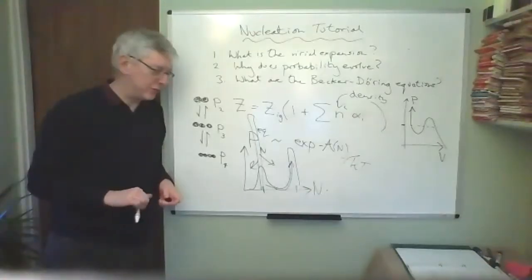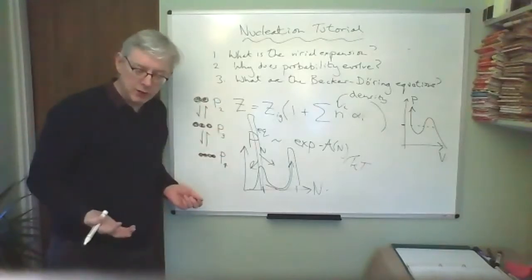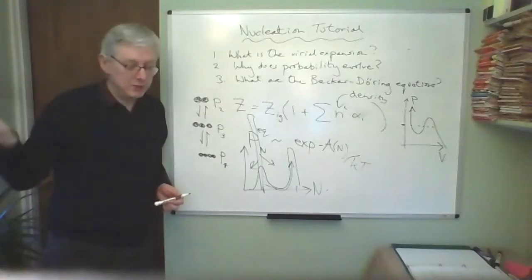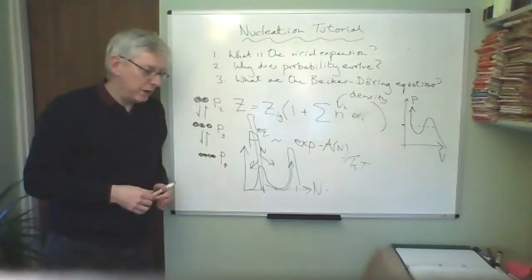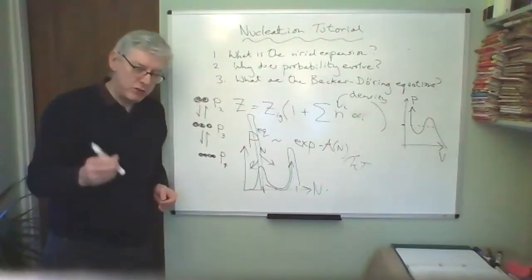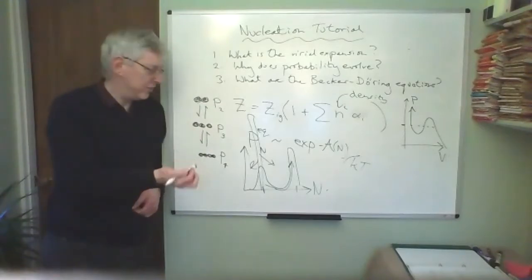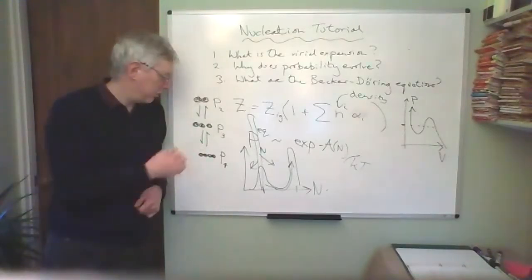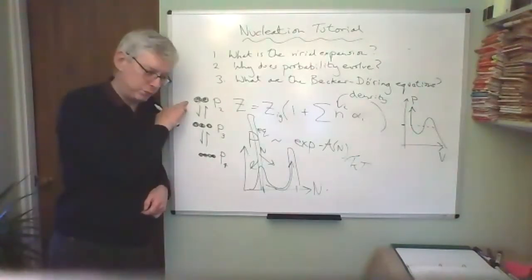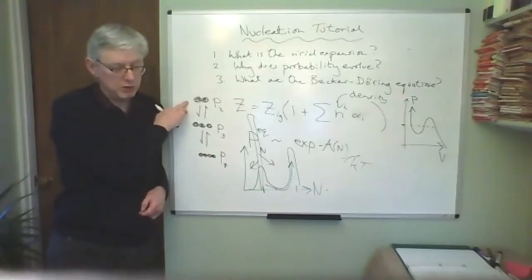Really good, thank you. That's spot on. It's a scheme for evolving these probabilities in a way that will model nucleation. It's simplified. It has to be, because it's a complicated business otherwise. But the simplifications are that the probability that the system should contain a cluster of size 3 depends upon the current probabilities, or I guess prior probabilities, that there was a cluster of size 2 present in the system.